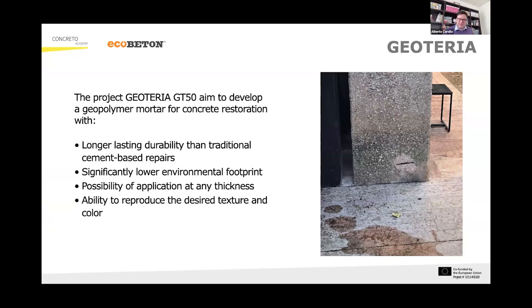Because what we notice is that once you repair the concrete, the repair does not last as long as the original concrete. It has a lifespan, and the repair lifespan is very short. We want to significantly lower the footprint, of course, and to have something that you can apply at any thickness. One property of geopolymer is that there is no water inside. It's not a replacement for cement. It's another thing. Cement is another mixture, and geopolymer, from a chemical point of view, is an ordered structure. So it's completely another thing.